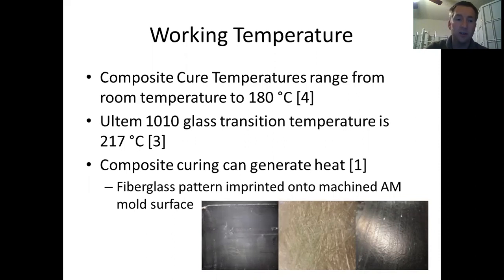And then another thing to keep in mind is that heat is generated as the resin cures in the composite. So one paper showed an example of their ABS polymer mold that they had made, and they had machined it. And then after curing their fiberglass composite, they had an imprint of the fiberglass pattern on their mold. And so that's something that you have to take into account as you are designing.